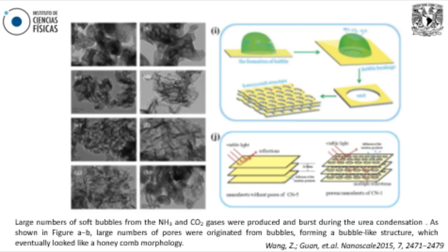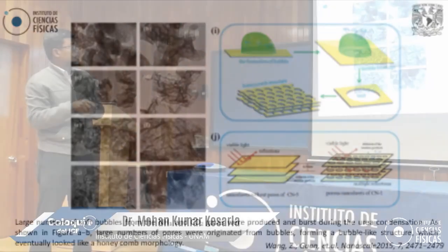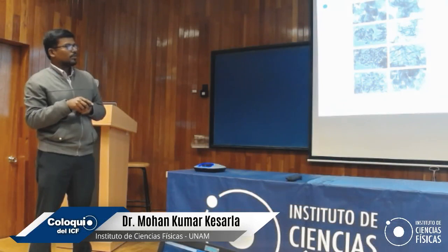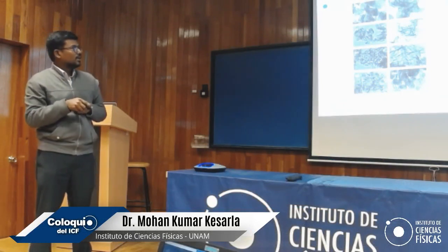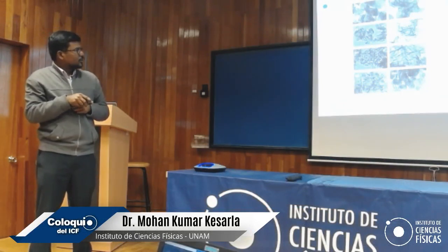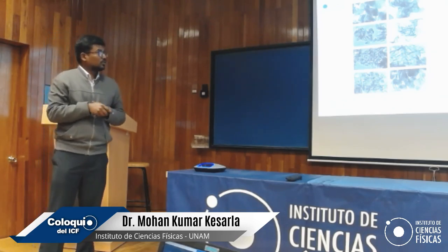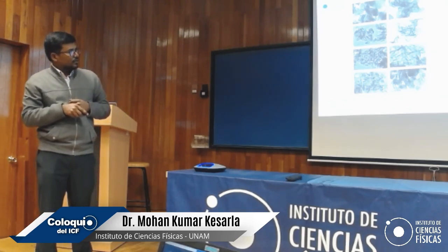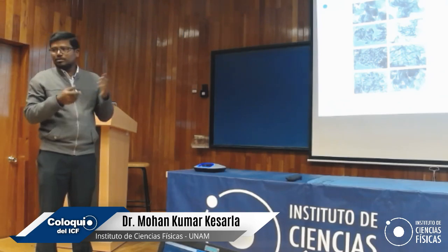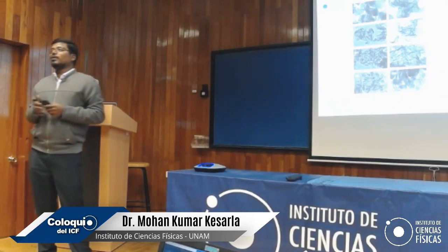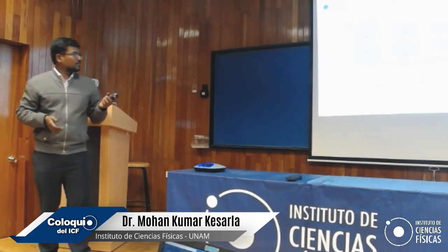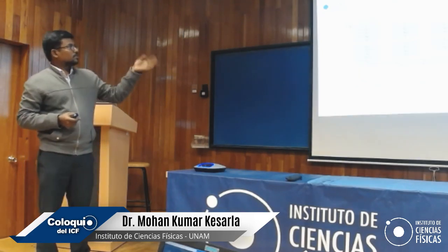So what happened here? During the process of this thermal polymerization, they introduced a few droplets of water, which creates soft bubbles by the ammonia and carbon dioxide being released, and it forms porous units on the surface, which they call a honeycomb surface. So what is the importance of this? The visible light reflections will be more, so it will be good for photocatalysis. That's the concept. And it is always better to exfoliate.